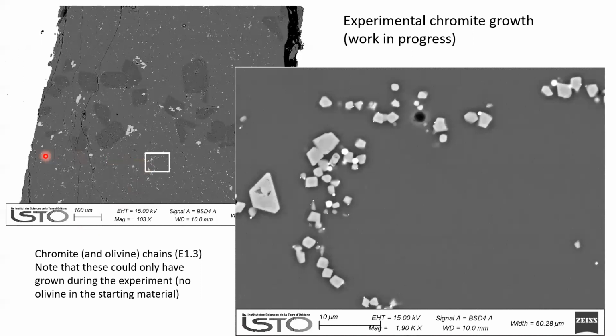So what are these things? Well, we had a lot of discussion about what these things mean yesterday. I won't rehearse all of that argument. What we originally thought was going on was some sort of heterogeneous nucleation, which is when crystals grow against a pre-existing solid substrate. We thought we were seeing evidence that chromite crystals were nucleating off pre-existing chromite crystals to form chains. And there are all sorts of reasons why that simple model isn't right.